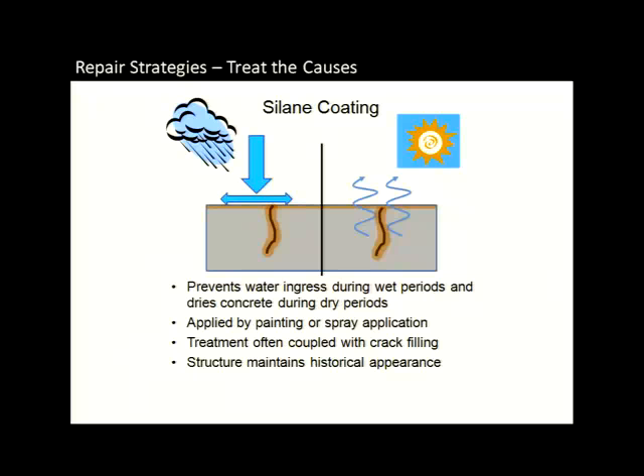So it takes time for the moisture to actually leave, and of course that depends on your relative humidity on the exterior of the concrete to be a driving force to pull the moisture away. But over time, you can effectively dry out a structure with these silane coatings. Obviously, as the structure gets larger, it's going to be more difficult to dry it out, so you may have to come back several times and reapply the silane coating, and you may have to epoxy inject and fill cracks that open up over time just from the reaction occurring. But if you can keep a maintenance plan where you're coming back every few years for 3 to 5 years with this silane type coating, you can effectively dry out most concrete structures to prevent ASR from happening.